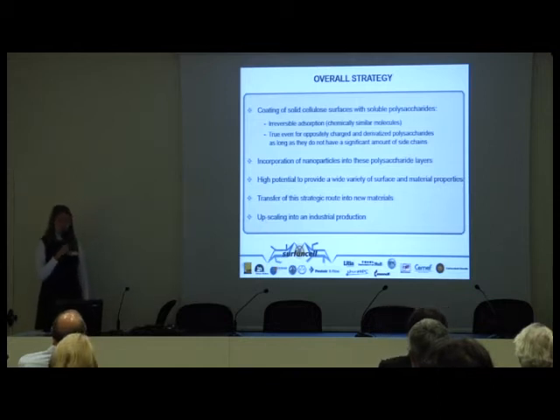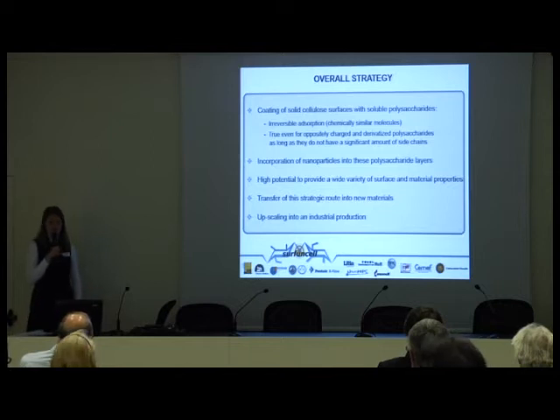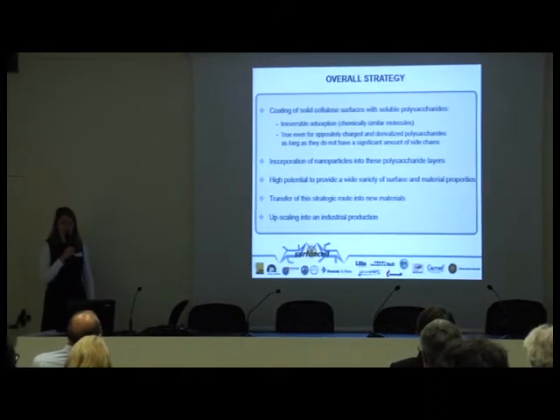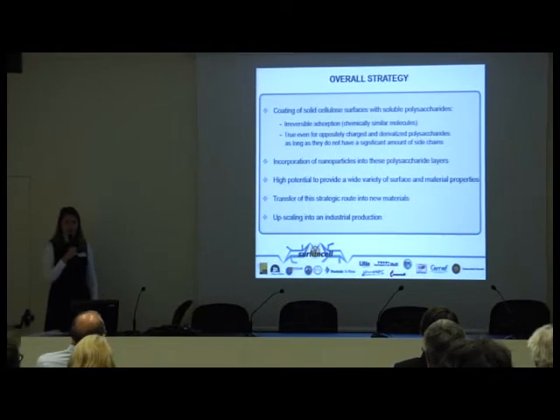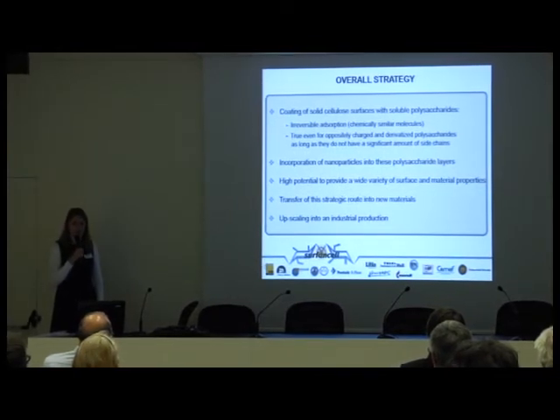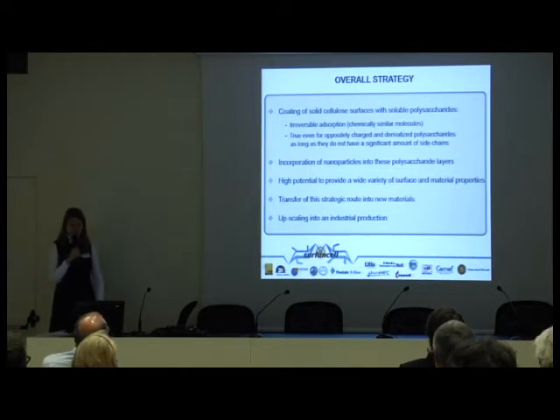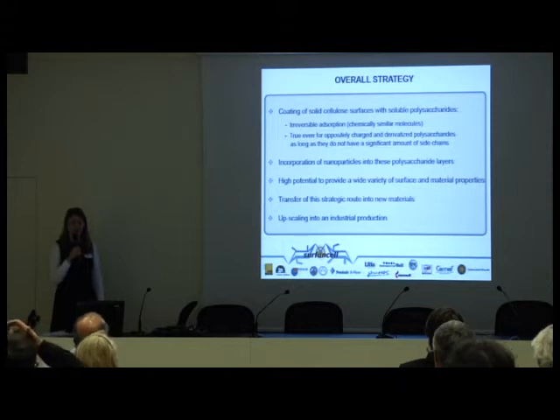Coming to the overall strategy, the aim is to coat solid cellulose surfaces with soluble polysaccharides, and this can be achieved in an irreversible manner due to the quite high chemical similarity between these molecules. This kind of adsorption behavior holds even for derivatized molecules, provided there is not a significant amount of side chains.